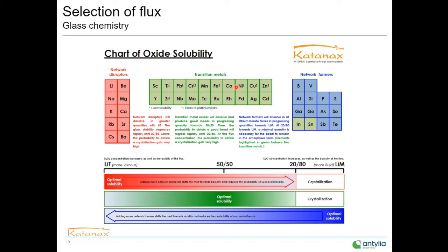You can see that it's pretty similar to a periodic table of elements, separated in 3 different color codes. So we will associate these colors to the elements present in your sample. In the middle here, you have the flux scale from pure lithium tetraborate to pure lithium metaborate, and the 50-50 blends, as I just showed you in a fume hood. What is important to keep in mind is that a type of flux will be better adapted to a type of sample regarding the optimal solubility, optimal fusion conditions.